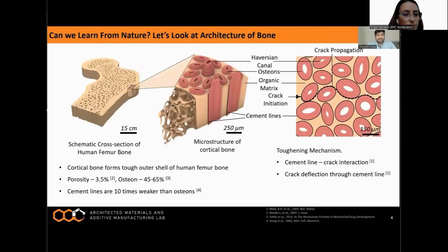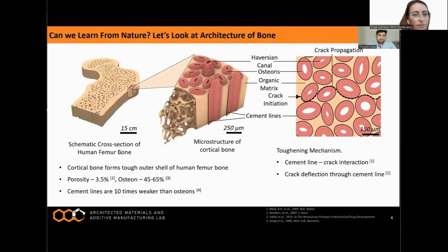Let's look at the microstructure of bone. The human femur bone is composed of outer tough cortical bone and inner porous spongy bone. The cortical bone has two orders of magnitude higher fracture toughness than its constituent materials, hydroxyapatite crystal and collagen. This increase in fracture toughness can be attributed to the presence of tube-like osteons embedded in the cortical bone.